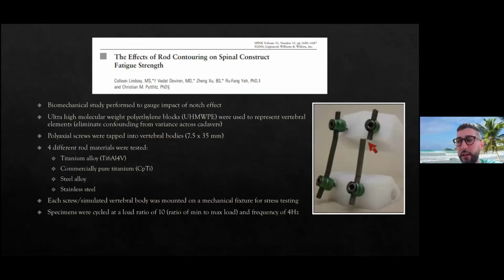I'm going to show you a lot of studies today, so we're not going to spend a ton of time on each one. I'm happy to send this along to you and reference it, but this is a biomechanical study. And basically they want to quantify this notch effect. And so obviously they can't use cadaveric bone to do this because you can't control for the density of the bone and the different anatomies. So basically, they create these polyethylene blocks to simulate vertebral bodies. They tap them with polyaxial screws, and they use 4 different rod materials: titanium alloy, commercially pure titanium, steel, and stainless steel. And they mount them for stress testing, and they cycle them at a load ratio of 10.